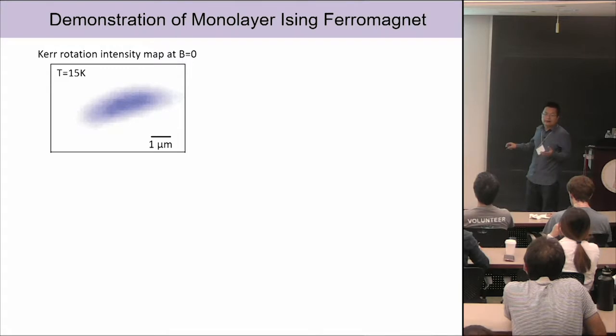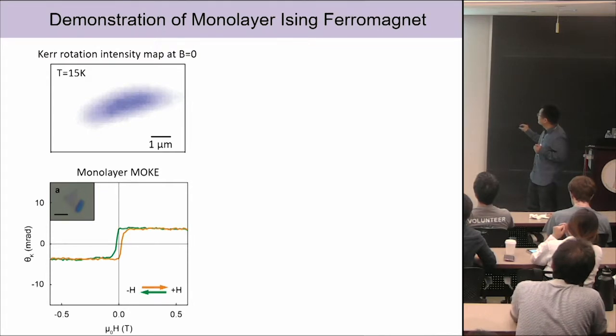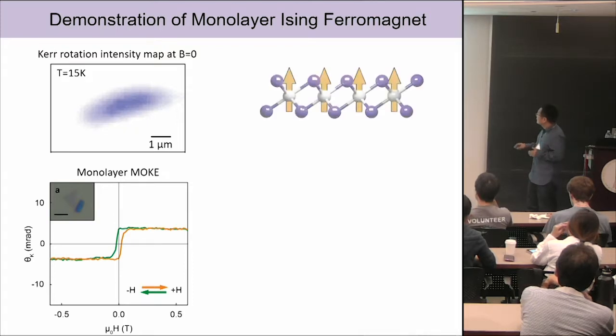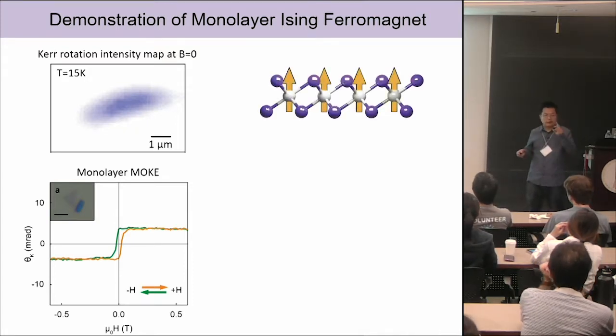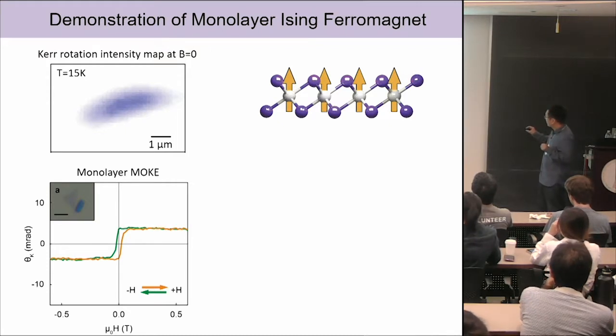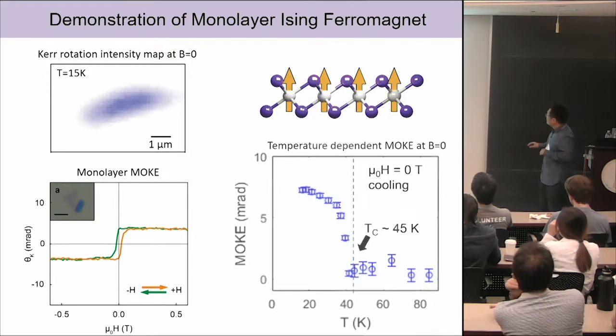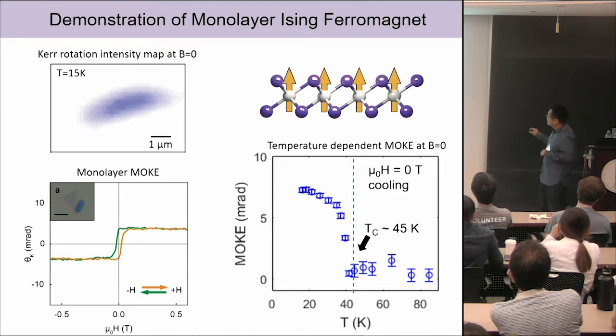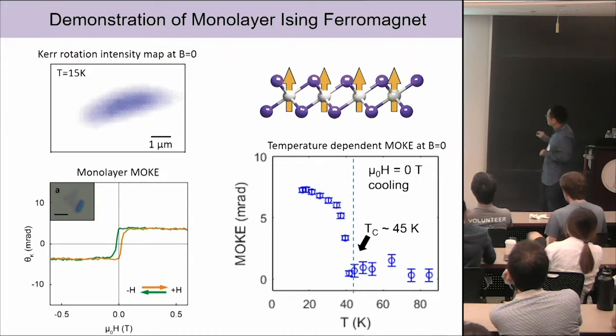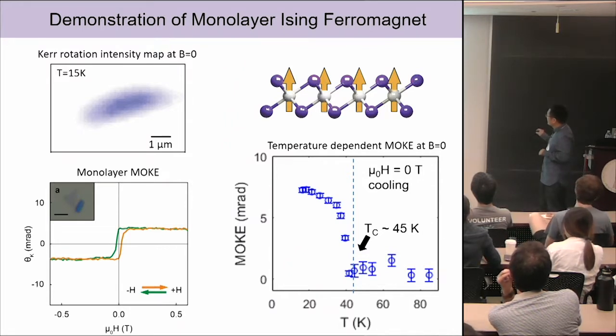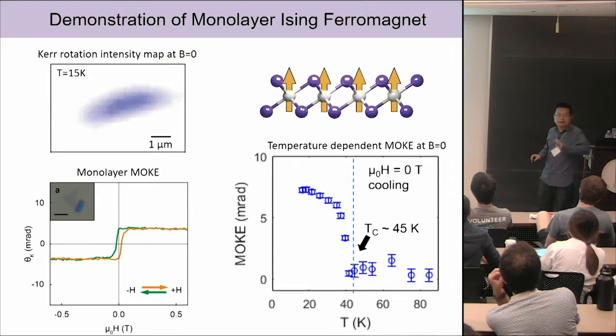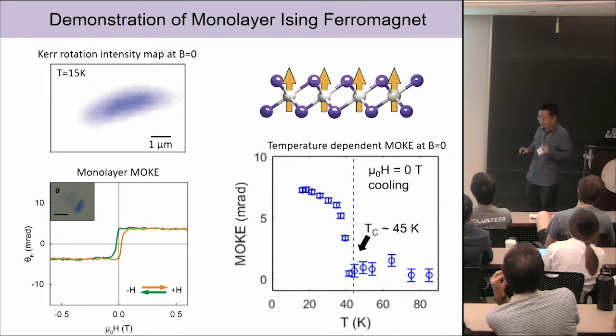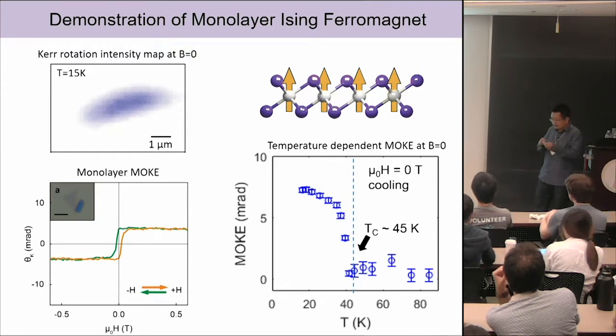But as I just mentioned to you, seeing a Kerr rotation signal doesn't mean we do have it. So we can park the laser at one spot on the sample, then scan the magnetic field, and then we see this hysteresis curve. So this does prove we have a ferromagnet with out-of-plane spins. It's actually an Ising ferromagnet for this particular example. We can also measure the remnant magneto-Kerr rotation signal as a function of temperature. This gives us a measurement of the Curie temperature in the monolayer. Actually, it's 45 Kelvin, not too far from the bulk crystal, right? It's about 60 Kelvin. So this just shows that this monolayer ferromagnet has pretty strong out-of-plane magnetic anisotropy.